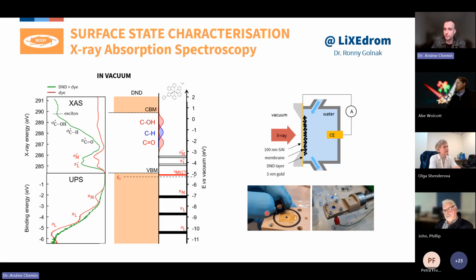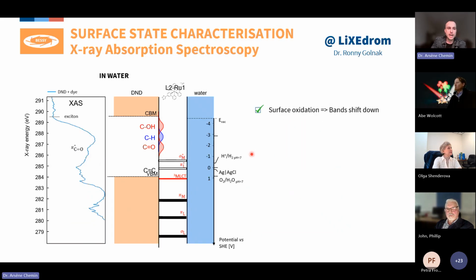So basically what we had to do is to deposit the nanodiamond on a very thin silicon nitride window of only 100 nanometers and put that into an electrochemical cell, and everything is actually under vacuum. So the X-rays go through the window, are absorbed by the nanodiamonds, and what we are detecting is the residual ionic current, which is created by this photoexcitation. And when we do that, we find an X-ray absorption graph, which is very different from the previous one.